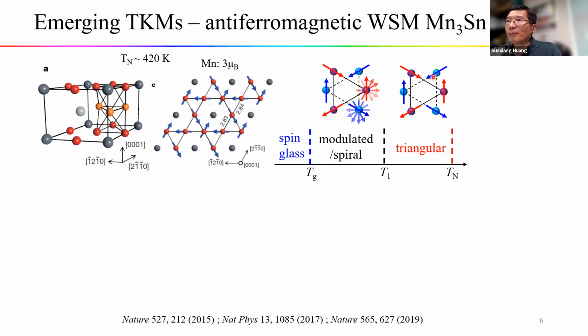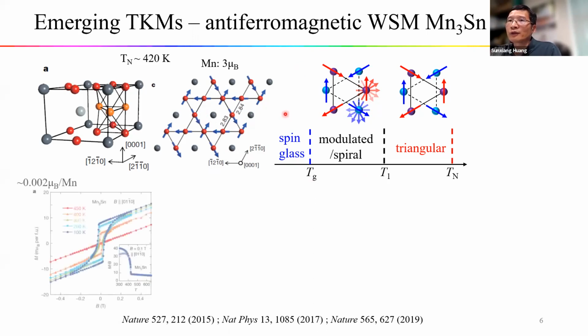So it is an antiferromagnet, so usually the net moment is close to 0. That's also the case here. Despite the manganese having a large moment of 3 μB, they have this nearly perfect triangular configuration, so the net moment is close to 0. But there's a little bit of tilting, so there is still a very small net moment. If we apply an in-plane field in the Kagome plane, this net moment can be switched. The direction can be switched, meaning the polarity is reversed. It shows in the magnetic measurement here when the field is along the Kagome plane.